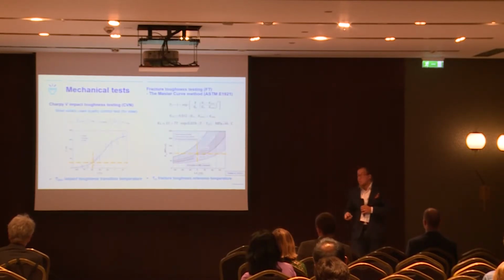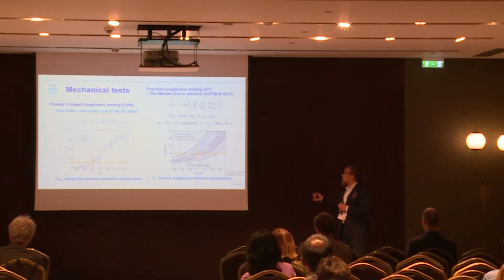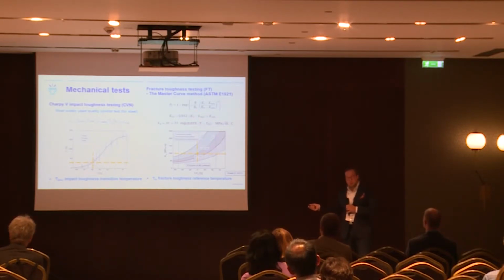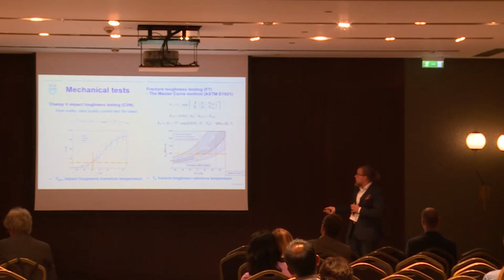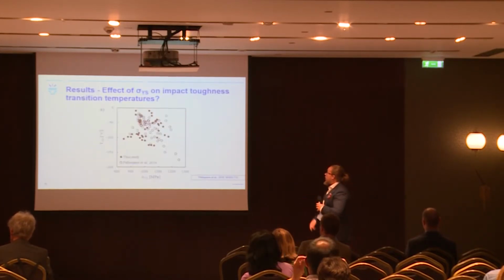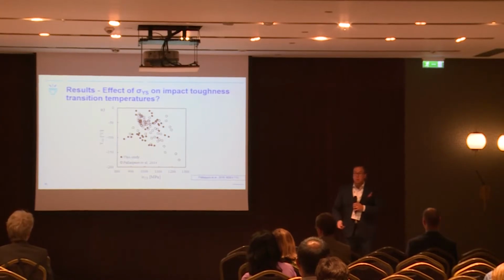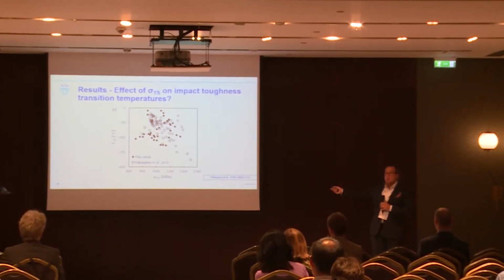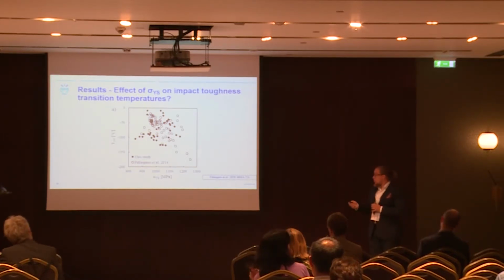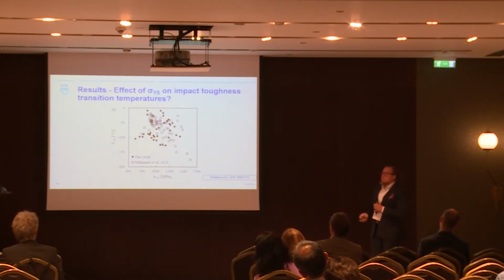For mechanical tests, we have used the standardized Charpy V impact toughness tests and standardized fracture toughness tests to get the ductile brittle transition temperatures: T27J or T28J in the case of impact toughness, or T0, the fracture toughness reference temperature, from fracture toughness tests. And as further motivation, when we plot our materials' yield strength against the impact toughness transition temperature, we do not see much.